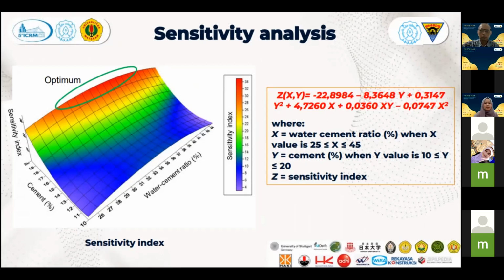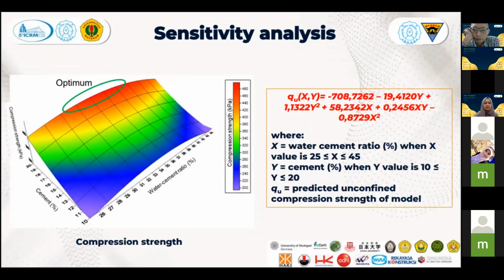The water cement ratio, cement, and sensitivity index can be plotted with the 3D statistical model. And the sensitivity index value can be obtained by using this figure or the equation as follows. The sensitivity index for the addition of 3% tire waste for a water cement ratio of 45% and 20% cement is 29.49. And then the third step of sensitivity analysis determines the optimum unconfined compressive strength for the addition of 3% tire waste for a water cement ratio of 45% and 20% cement using the 3D statistical model. The model can also be predicted using the following equation or figure as follows. The predicted unconfined compressive strength is 430 kilonewton per square meter with the proposed equation.